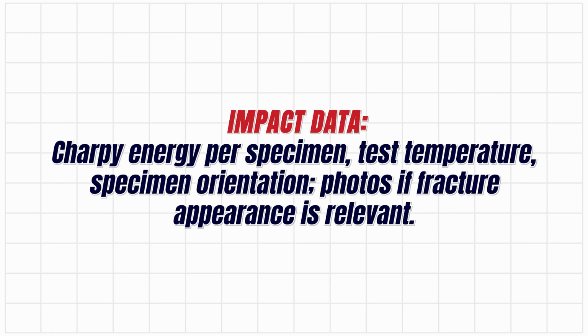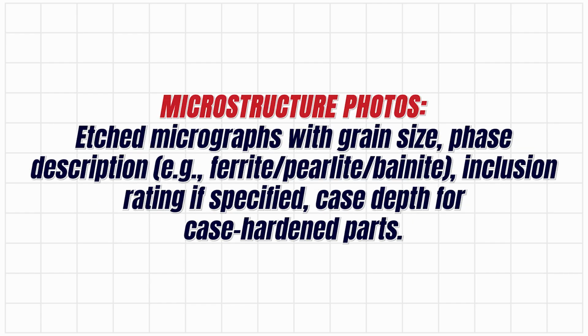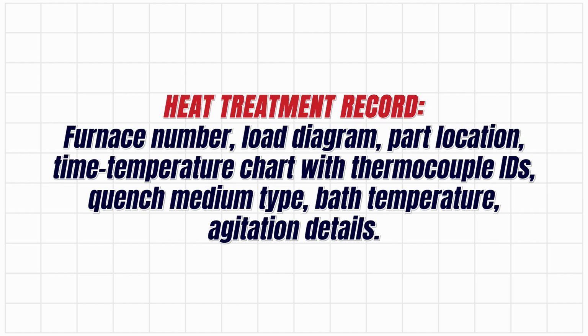Impact data: Charpy energy per specimen, test temperature, specimen orientation. Photos if fracture appearance is relevant. Microstructure photos: etched micrographs with grain size and phase description, for example ferrite, pearlite, bainite, and inclusion rating if it is specified. Case depth for case-hardened parts. Heat treatment record: furnace number, load diagram, part location, time-temperature chart with thermocouple IDs.